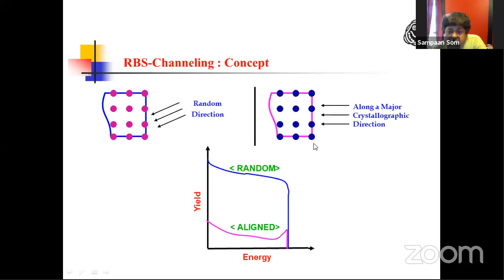One is known as tilt. The crystal can be rotated with respect to the incident ion direction, okay? One is continuous azimuthal rotation, and another is with respect to the sample normal. So with three possible directions, the ions can be channeled through the axis of the crystal. In the ideal condition, when the ions go along the crystal axis, they always pass through the space in between the strings of atoms. So where are the scattering centers? They will be drastically reduced.